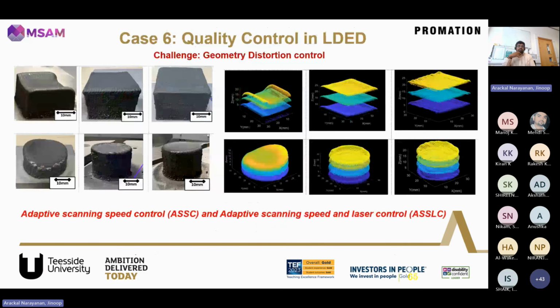The next step of work was to control this deviation. So we could predict it, now how to control it. This was an algorithm developed by my colleagues Farzan and Kaji, where we could control the scanning speed and the laser power during manufacturing in such a way that we could achieve a flat surface. This is the original structure, and once we adjusted the scanning speed and laser power, we could get flat surfaces with a higher quality.